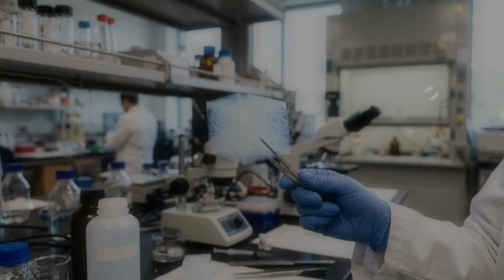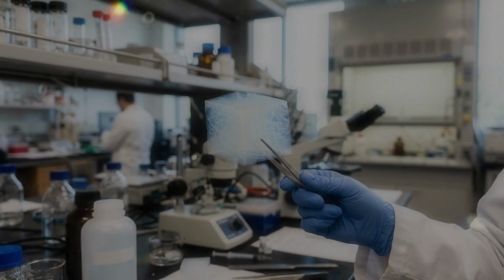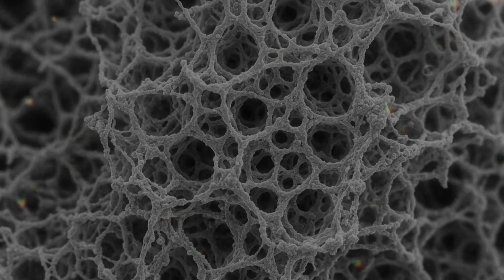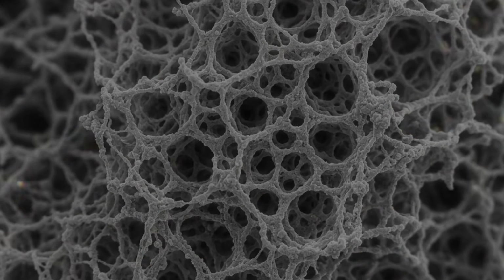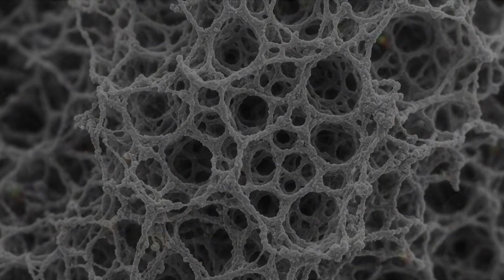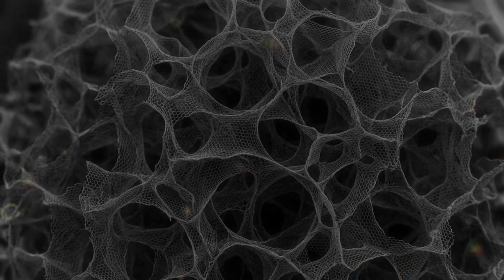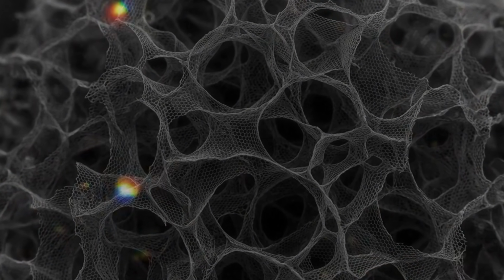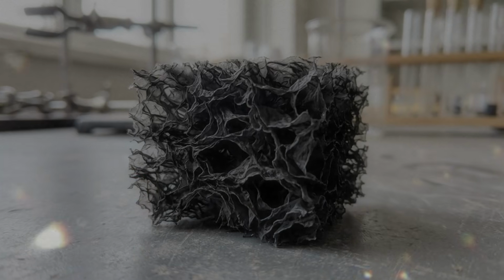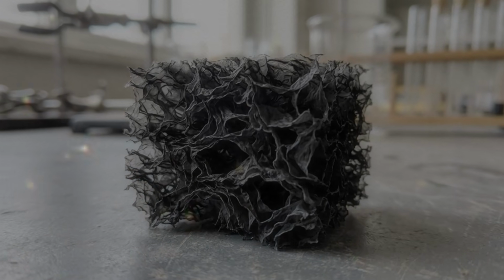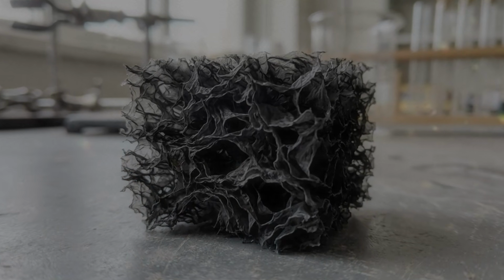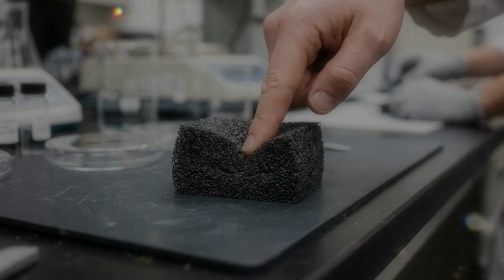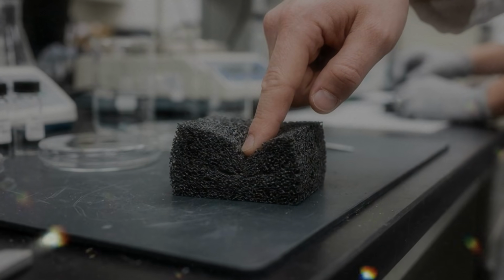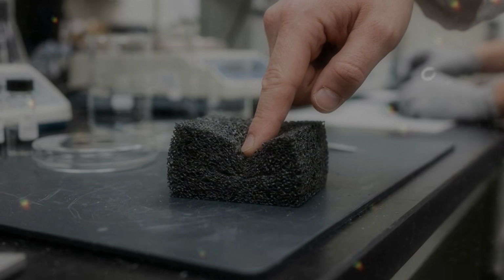This reveals a continuing tension in the design. Lower density requires less solid carbon. Less carbon means thinner walls and fewer connections. Eventually the framework becomes too weak to keep its shape. Increasing the amount of carbon improves the number of load-carrying paths. It can increase electrical conductivity and make the material easier to handle. It also adds weight and may reduce the open space available for liquids and gases. The lightest record sample is therefore not automatically the most practical version.